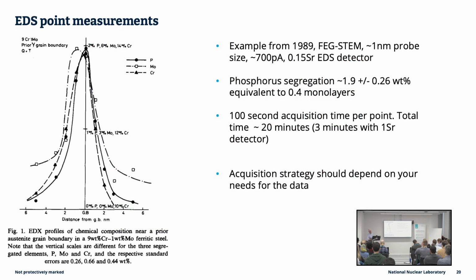And this example goes back a long time to 1989 from some of my colleagues at Harwell, when we were using the old vacuum generators STEM that we had, which would produce about 1 nanoamp into more or less a 1 nanometer probe. In terms of the electron optics of the system, it was brilliant for the day. The X-ray detector, however, was pretty tiny, as you can see. And to acquire the data, this data set would have been an array of maybe a dozen static points across a grain boundary.